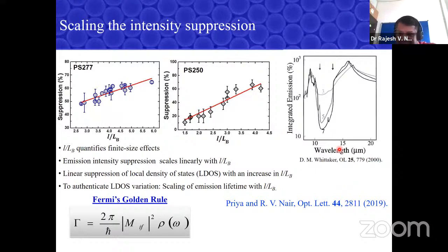And we know the reason why it was rejected. We knew even before submission that there is a problem with this result. We claimed that the spontaneous emission has a finite size scaling, or a size dependent scaling, in the system. The reason is, if you want to talk about any change in spontaneous emission, intensity is just a signature only. One cannot quantify just with the change in emission intensity that my emission is controlled or changed. Because if you have a light in your lab or room, you put a glass plate, the intensity is reduced. That does not mean that the emission from the emitter is altered. That is because of the filtering effect.